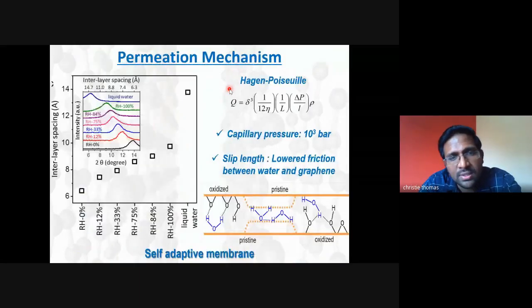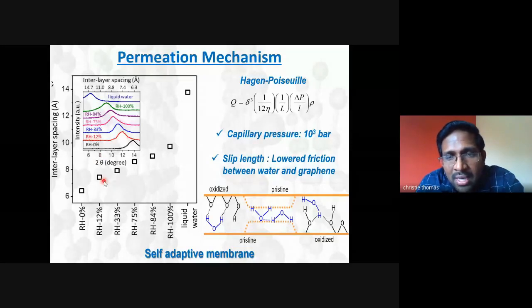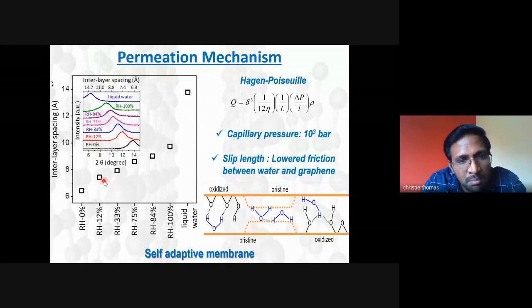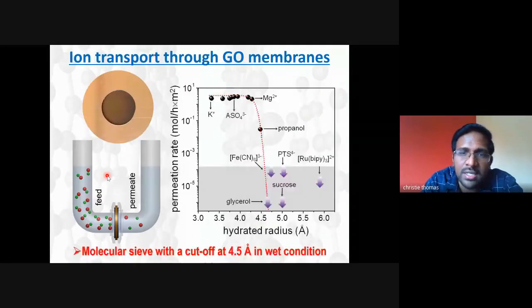As I showed you in this graph, if the interlayer spacing is less than 10 angstrom, you can possibly cut off salts. But I won't get interlayer spacing in this range, because when I put the graphene oxide in water, because we always do experiments in water, right? It swells. So if I can restrict the swelling, it would be great.